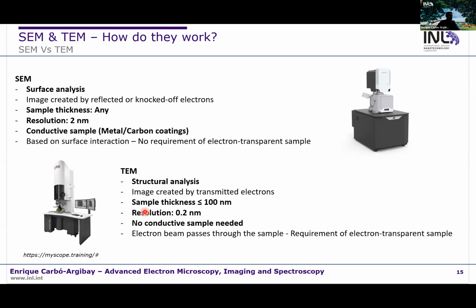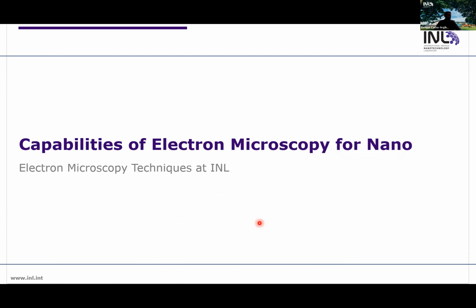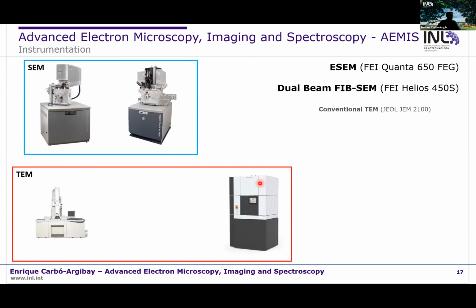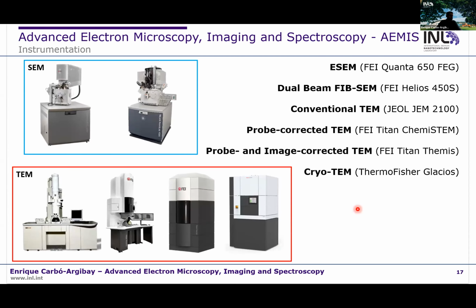However, in TEM, the sample thickness must be below 100 nanometers, so the sample prep is a bit more difficult, but the resolution and the structural information we get is better. We can go deeper in terms of imaging resolution, and we don't need conductive samples. This is the advantage. So some examples of these machines.